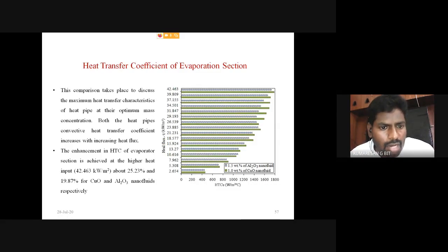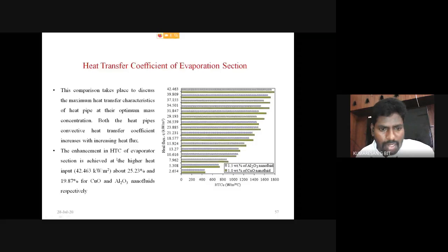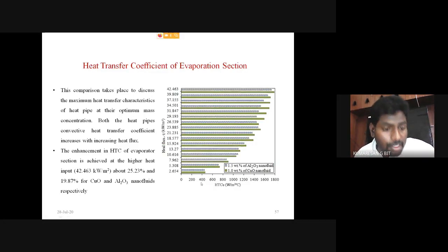Both the heat pipes' convective heat transfer coefficient increases with increasing heat flux. That enhancement in HTC of the evaporator section is achieved at the higher heat input of 42.4 kilowatt per meter square. At this heat flux it is about 25.23%, and for the aluminum oxide heat pipes it achieved only 19.87% for the same operating condition.